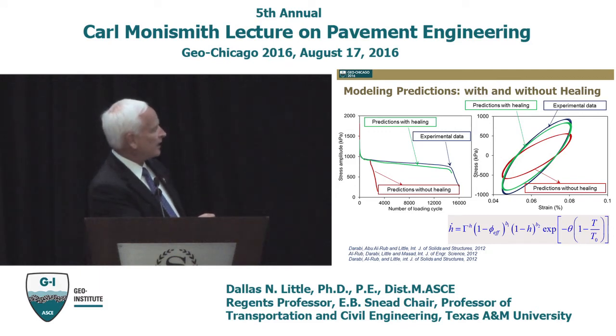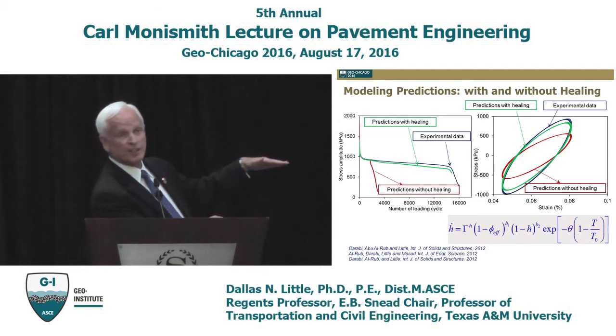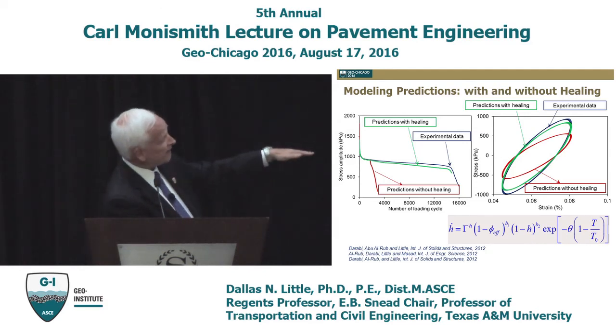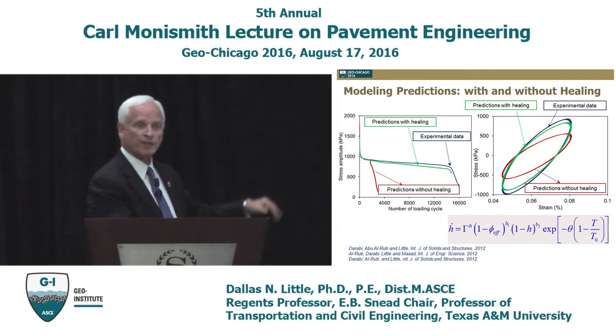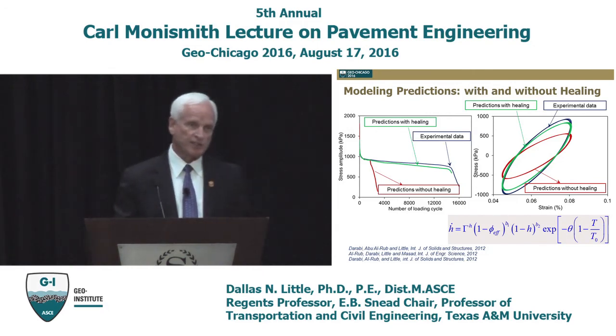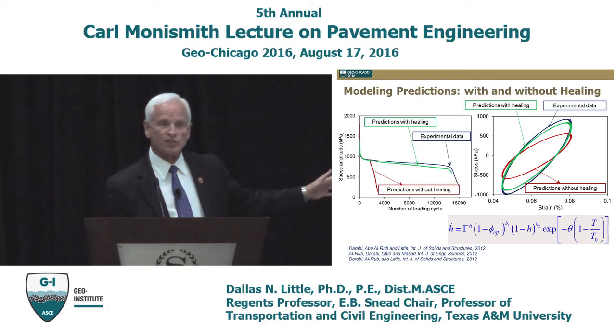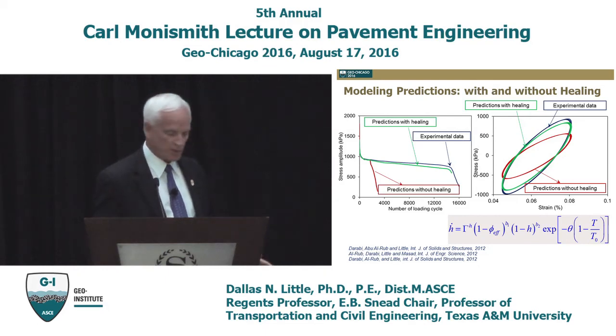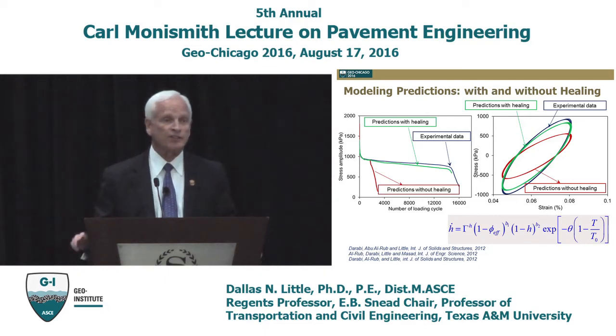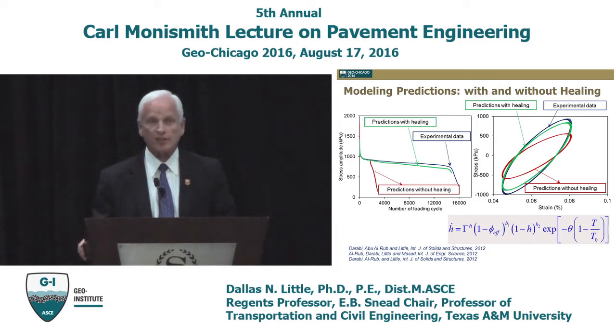It's pretty complicated looking, but essentially it says that the rate of healing increases as temperature increases. This is sort of an Arrhenius function down here. As the healing increases, the rate of healing decreases. It's kind of asymptotic. And as damage increases, the rate of healing decreases. So it's a logical healing function and one that we use to correct for the effect of healing in the damage process in Panda.